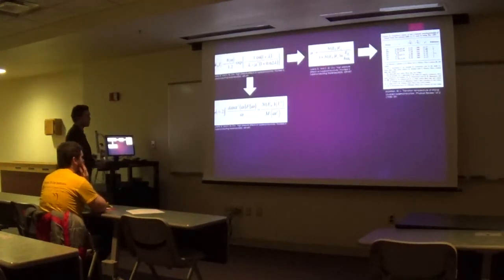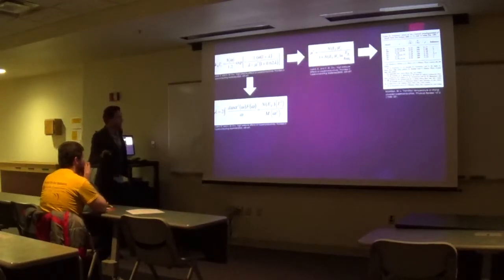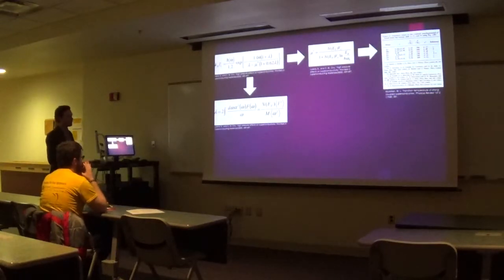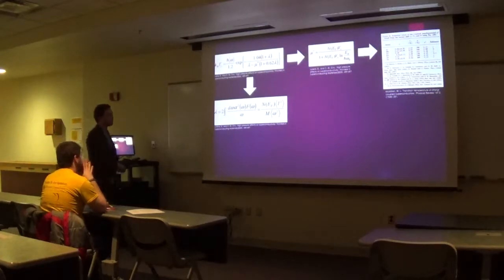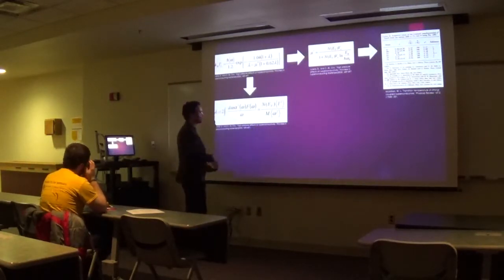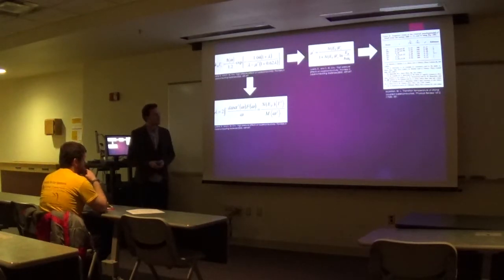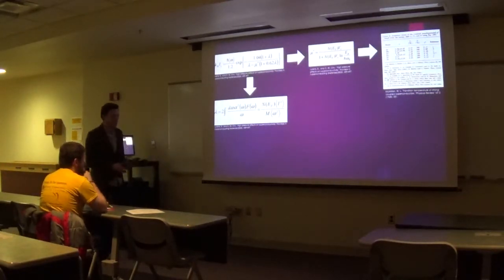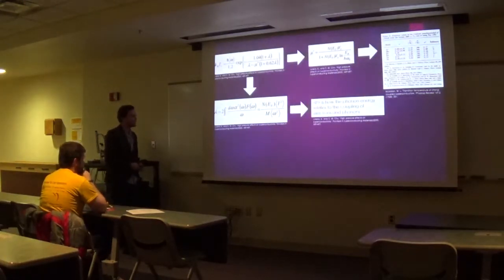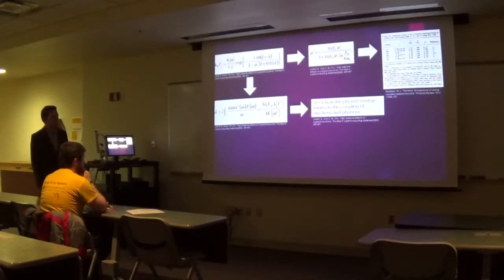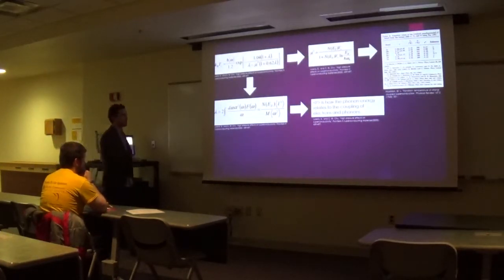So we can make the assumption that our mu star is going to remain relatively constant at 0.1. Now we're going to look at this lambda term right here. Lambda isn't wavelength. Lambda is what's called our electron-phonon coupling constant. We can think of it as the total amount of electron-phonon coupling occurring in our superconductor. If we sum this integral, we get these four terms: N(E_F), I squared, M, and omega squared. Omega squared is our phonon frequency. M is just the mass of the metal. The I squared term has a really long, convoluted, technical definition, but really it is how the phonon energy relates to the coupling of electrons and phonons.